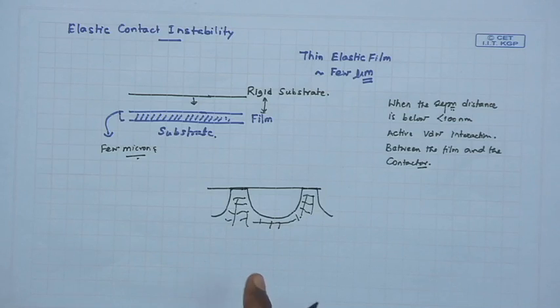In case of dewetting, we talked about a competition where the surface tension tried to stabilize the film, and your disjoining pressure tried to destabilize the film. Here again, this disjoining pressure was originating from van der Waals forces. Here again, the van der Waals forces are trying to destabilize the film. Here the only form of destabilization is that it is trying to come in contact quickly with the film. However, because it's an elastomer, because it's a cross-linked film, the physical cross-links present within the matrix in fact try to pull back and oppose this conformal contact, or the film surface moving towards the contactor, which is exerting attraction.